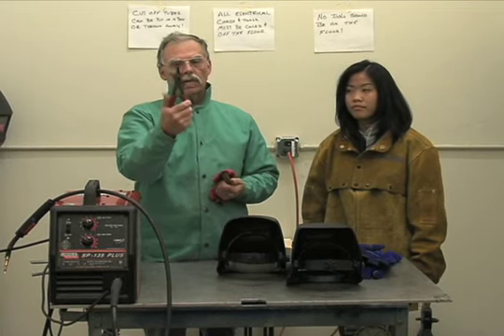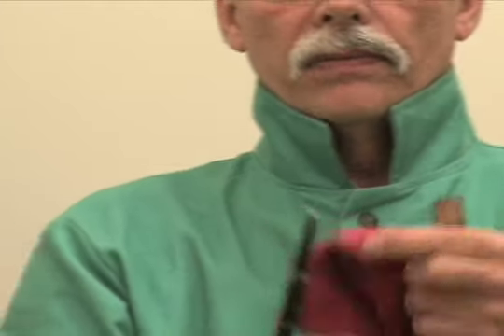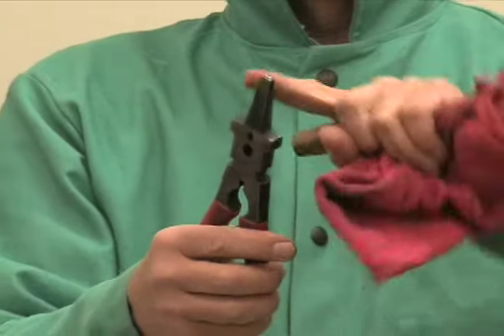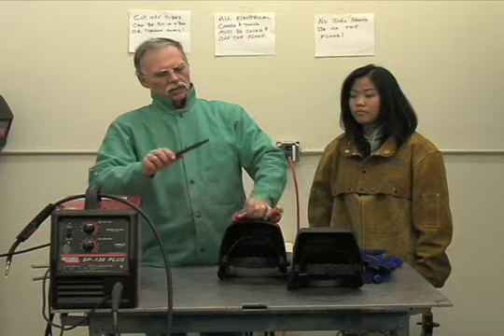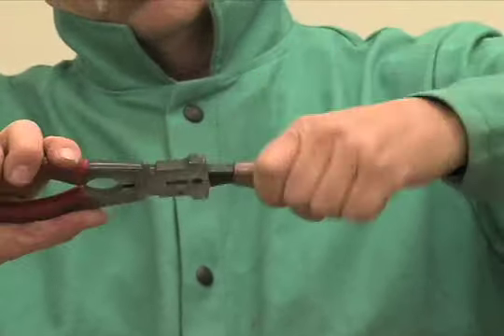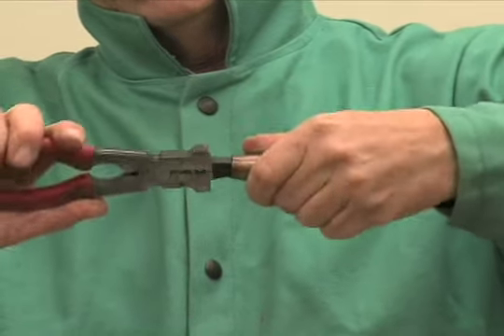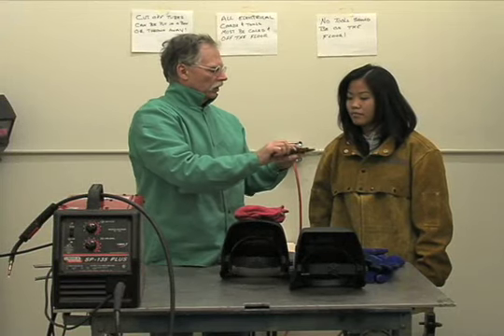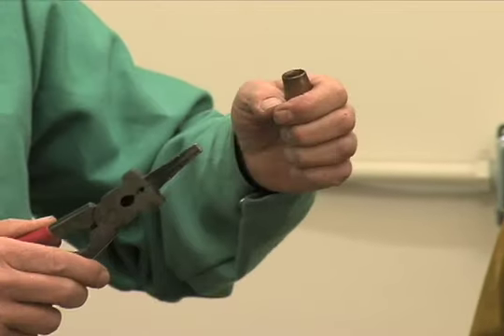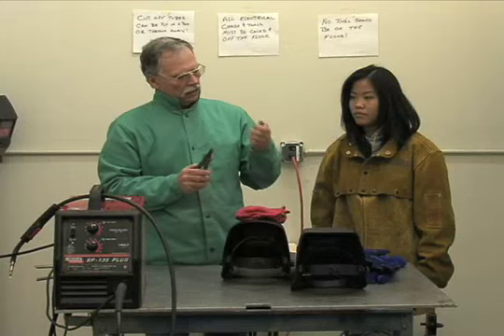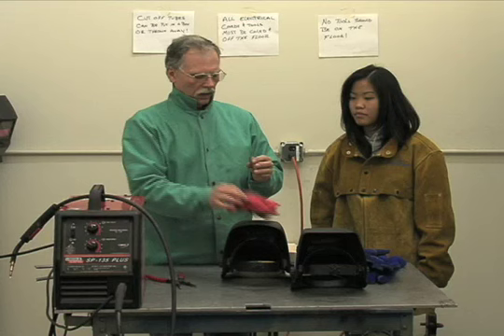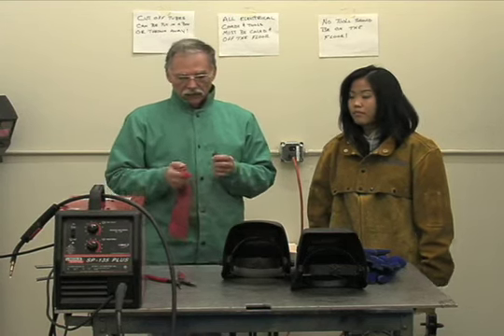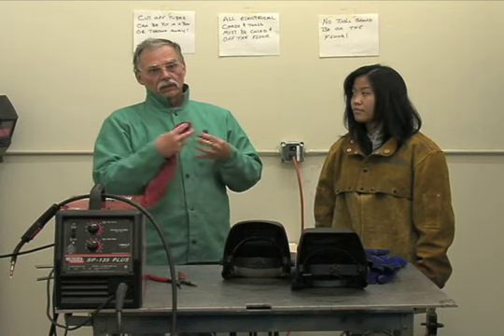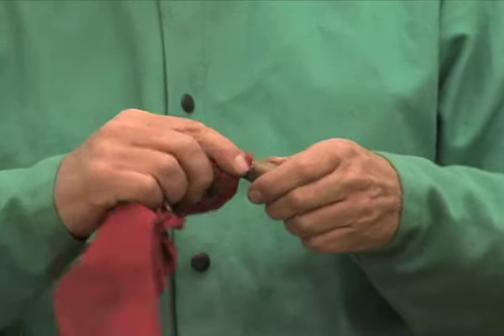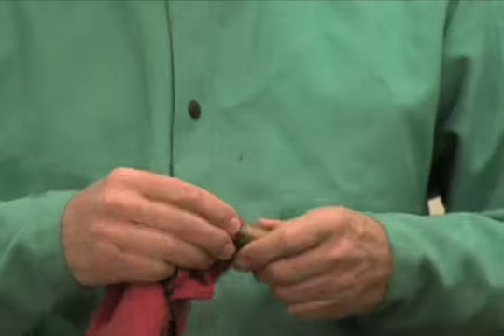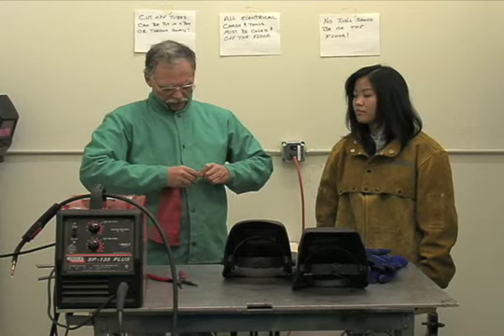Here we have MIG pliers. These MIG pliers are very special. They have on the tines here, they have sharp outside edges. These sharp outside edges are for insertion into the nozzle and rotated, and it will scrape away any of the steel BBs that are caught up and crunch. You can see the buildup here that's coming off. So you loosen them all up. If that is allowed to build up, it affects the purge gas flow. It causes the tip to run hot. If the tip runs too hot, the wire will melt coming out, and it will wad up, back up, and it'll stop feeding wire into the weld. And you have to shut down, and then you have a real mess to clean up.